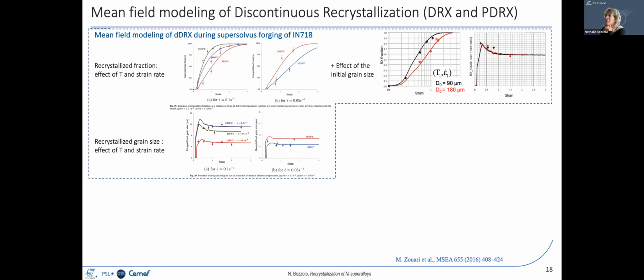So indeed, the recrystallization kinetics are affected by the initial grain size, simply because we are dealing with the necklace discontinuous dynamic recrystallization. And since the new grains appear on the former grain boundaries, if the initial grains are smaller, you have more grain boundaries, therefore more nucleation sites, and the recrystallization goes faster. But this doesn't change the recrystallized grain size. So all these effects are known and retrieved with such models.